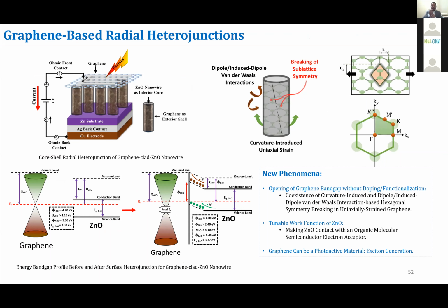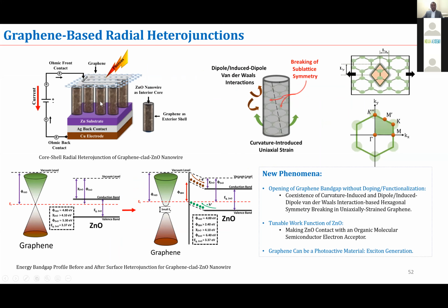Here is a structure where we have a nanowire, for example, zinc oxide nanowire, and we can wrap or clad a layer of graphene on top. And instead of creating planar junctions, we are creating radial junctions. So here photons can be confined, as well as we can build many such structures. In case of a planar junction, there can be one junction, but in case of a radial junction, you can create an ensemble of such structures that can lead to higher photovoltaic performance.